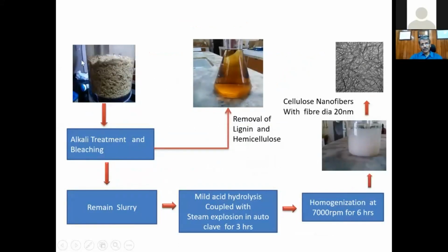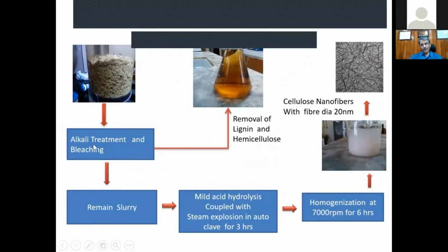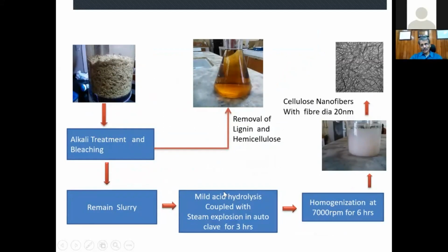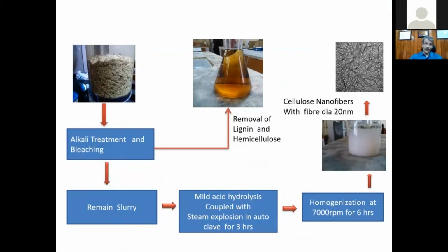Look at what we do in our laboratory. My PhD students collect agricultural waste from plantations, clean it, and chop it into smaller lengths. We treat it with alkali to remove lignin and hemicellulose, and you get a slurry. Then we go for acid hydrolysis, either with a strong acid or a weak acid. If you use strong acid, you get nanocrystals. If you use weak acid, you get nanocellulose.